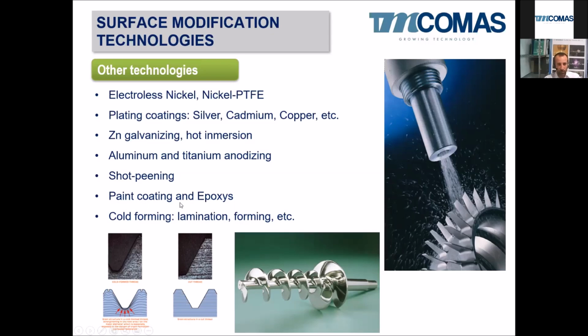Painting, coatings, and epoxies like Loctite or Belzona are very used in pumps and in other oil and gas applications to protect parts from corrosion and wear. Also cold forming, like lamination. We use lamination for reciprocating compressor rods to fabricate the threads. These threads are not machined in the lathe. They are cold formed, laminated, to create a compressive residual stress at the bottom of the thread, to avoid the appearance of fatigue cracks in the thread.